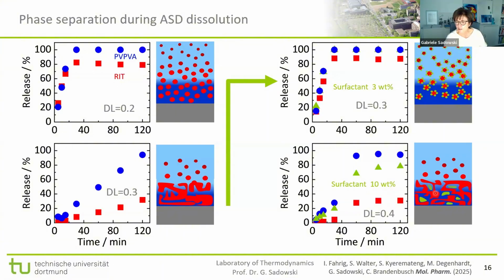One is ritonavir rich, then the blue one, which is rich in the polymer, and a surfactant rich phase, which is the green one. And if the surfactant is forming a separate phase, it doesn't care about stabilizing the droplets anymore, and so we have our old problem back. That means surfactant is nice, but it does not help if we have too much of the surfactant in it.